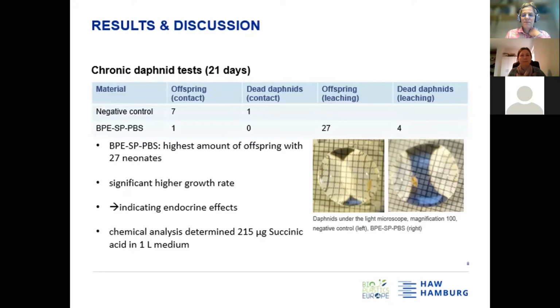So we also analyzed the medium, and we found 215 micrograms succinic acid in 1 liter medium. And succinic acid is a compound which is also produced in the Krebs citric acid cycle of cells. And from succinic acid, a kind of energy was produced. So this might be the reason why we have such strong growth effects of the material.